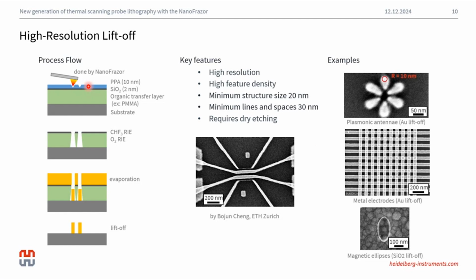So the resist stack, in this case, we call it the high resolution resist stack. And what we do is thin down the top PPA layer to allow us to get higher resolution. And also we introduce a silicon dioxide or any other hard mask thin film in between the top PPA layer and the organic transfer liftoff layer underneath.